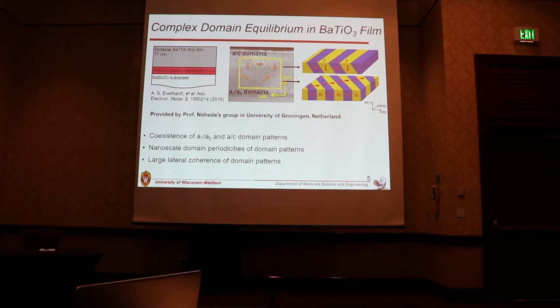I would like to note that this is not caused by lattice relaxation along the in-plane direction, because we have seen that the in-plane lattice parameter is consistent throughout the system. This coexistence of two different domain patterns indicates that the system is at the domain phase boundary, which is quite great for us to study transformations. Also, these domain patterns have nanoscale domain periodicities and a large lateral coherence, which provides us the opportunity to use the X-ray diffraction method to study domain patterns.